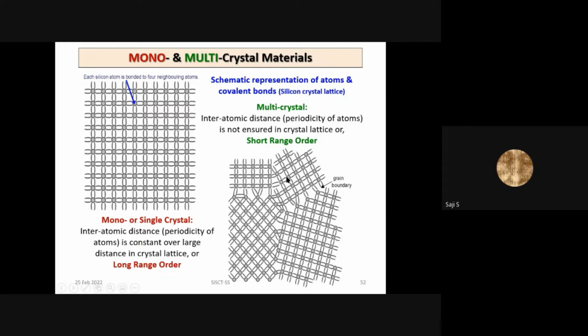Whereas in the multicrystalline material, the order is very short range. It is very, very short. For example, you have different grains forming the crystal, and the boundaries are always broken atomic bonds. So the movement of carriers is not free. There'll be recombinations at these junctions where the grain boundaries are, and this can create problems or long-term performance issues. So always the technology is centered around single crystalline material, and the conversion efficiencies for solar cells are higher for monocrystalline wafer compared to multicrystalline wafer.